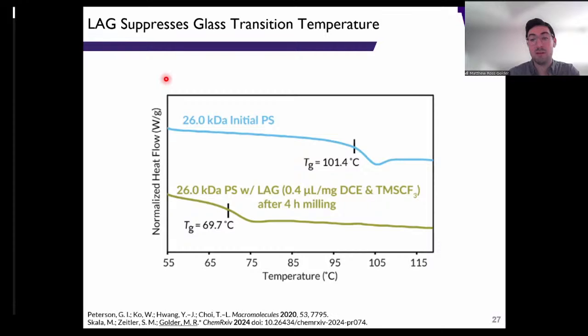So we selected a polystyrene that was above the limiting molecular weight. This is a 26 kilodalton polymer that has a glass transition temperature of about 101. And we saw that when we mixed in our liquid reagents, our small amount of lag solvent and our small amount of liquid trifluoromethylating reagent, and we mix them around for a bit, we see about a 30-degree decrease in glass transition temperature. So this was pretty good evidence to us that we could potentially plasticize our material just through